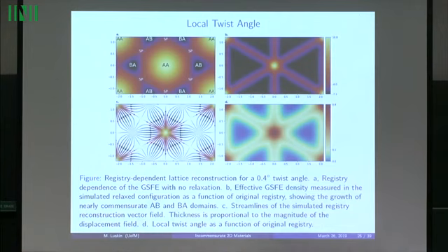At the AA points we see a positive divergence, a very dense number of lines coming out of there. That means we have high twist at the AA nodes, and then large regions of slow untwisting in the AB and BA regions.